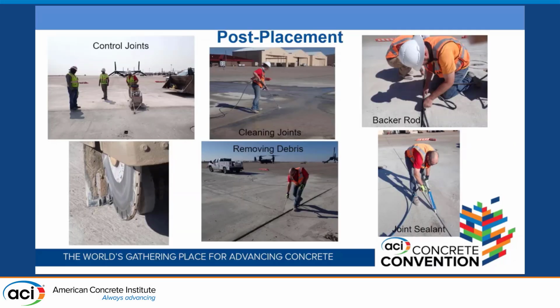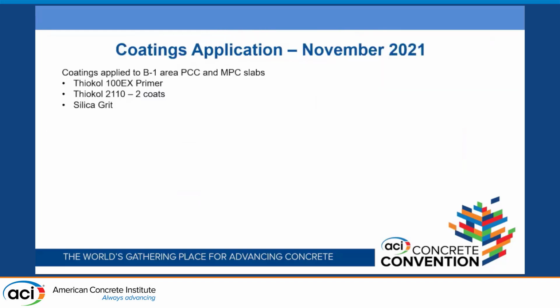So after placement, we came back and cut in some control joints. As far as the MPC is concerned, a lot of the control joints were just cut where existing joints were. And so we wanted to keep that the same. There's the cutting wheel, cleaning the joints, removing debris, installing backer rod, and then installing the joint sealant. And then coatings applications occurred in November of 2021. We had a couple folks go out. Those are the different coatings they applied, and then also a silica grit mixed into it.